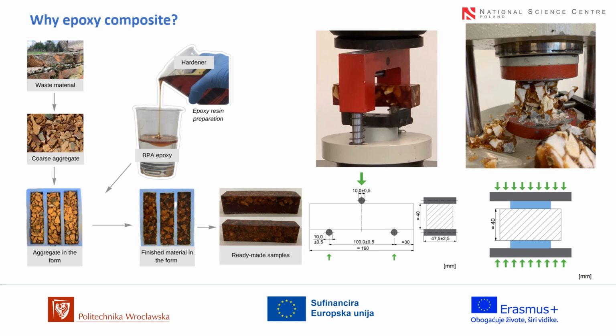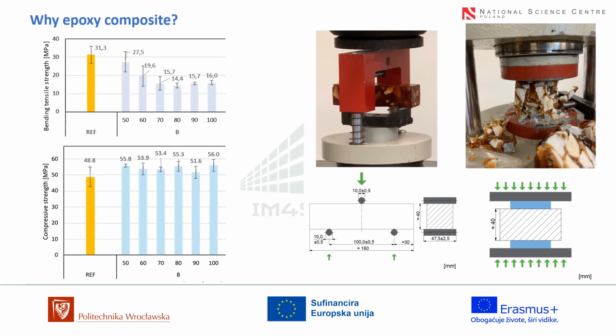Furthermore, we subjected these epoxy brick composites to mechanical testing. The performance was outstanding. The flexural strength results demonstrated that the ceramic particles form a very strong mechanical interlock with the polymer matrix. This also results in numbers where the bending tensile strength is much higher than typically for concretes. Furthermore, the compressive strength of these epoxy brick composites exceeded 50 megapascals and sometimes reached even up to 60. This incredible mechanical capacity opens up high-end structural applications. For instance, these materials are ideal for heavy-duty industrial flooring, chemical-resistant linings, structural repair mortars, and high-precision precast elements.